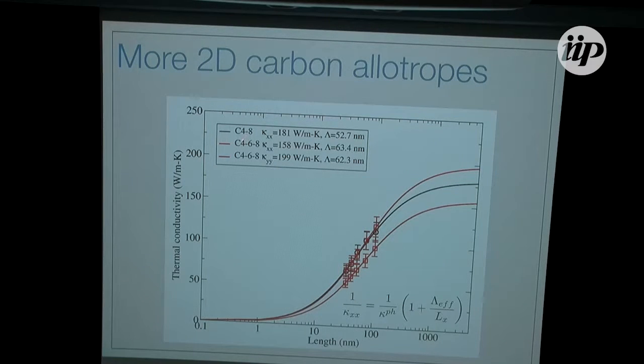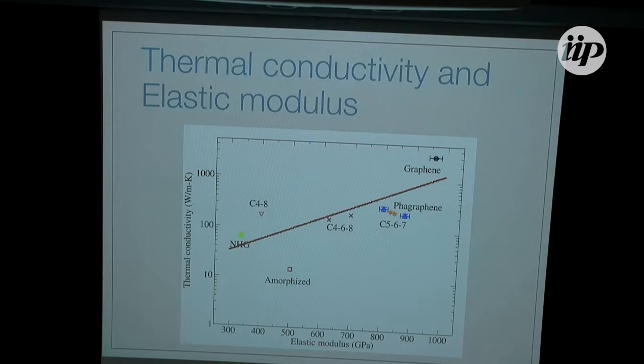When I add the 4-6-8 structure, again I find an anisotropy in the thermal conductivities. And then when I add the Haeckelite, the 567, there appears to be a very small anisotropy in this case, but it's less than 10%. I'm not including the error bars here, but they are around that order. So I wouldn't say that this material has anisotropic thermal conductivity.